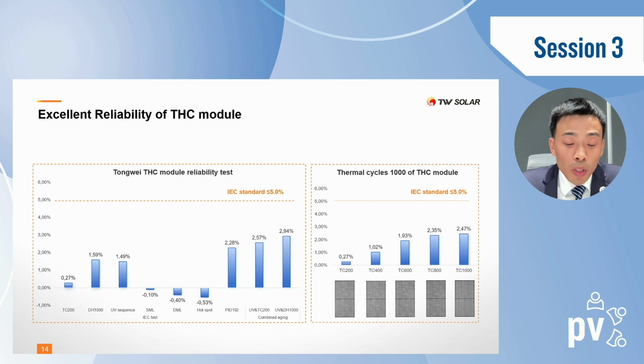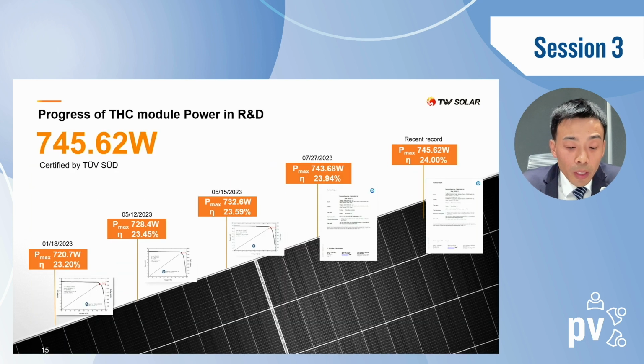Our THC modules have achieved excellent performance, not only on IEC standard reliability tests, but also combined aging tests such as UV plus thermal cycling and UV plus damp heat. Even in 5 times IEC reliability tests, such as thermal cycling 1000 test, the module power degradation is less than 2.5%. With HJT technology from wafer to module developing accumulation, we have broken Tongwei's HJT module power record 5 times this year, from about 720 to 745 watts, which is certified by TÜV SÜD.